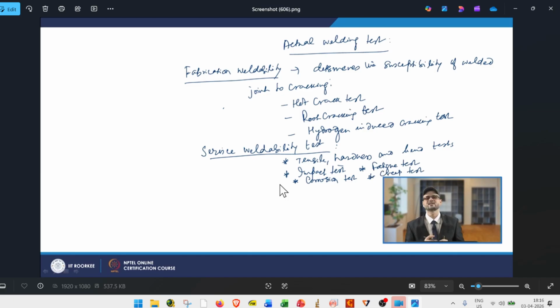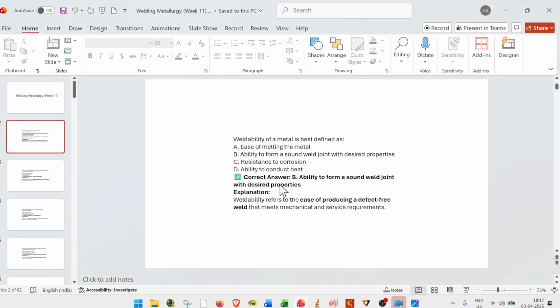In that one we can classify them into two ways. One is the fabrication weldability and the other is the service weldability test. In the fabrication weldability test, we can do hot cracking testing, root cracking testing, hydrogen induced cracking testing. In case of service weldability testing, we can do the impact test, fatigue test, creep test, corrosion test, tensile, hardness, bending test, impact test. Such kind of tests we can perform. So based on this, we can see some of the problems.